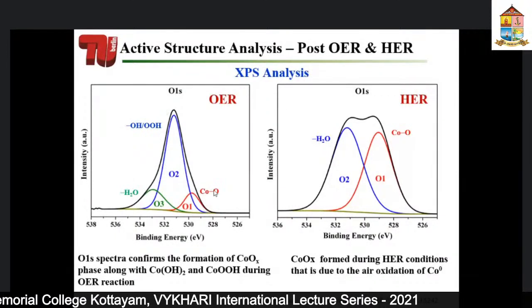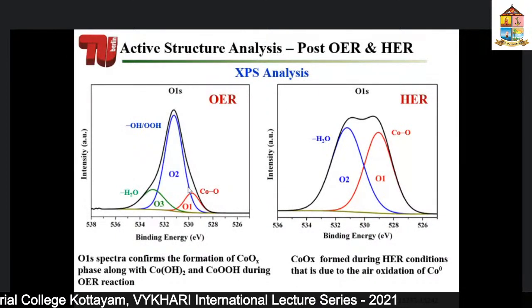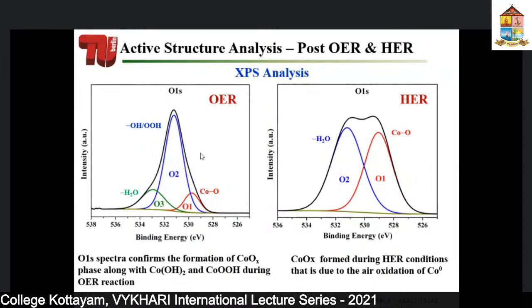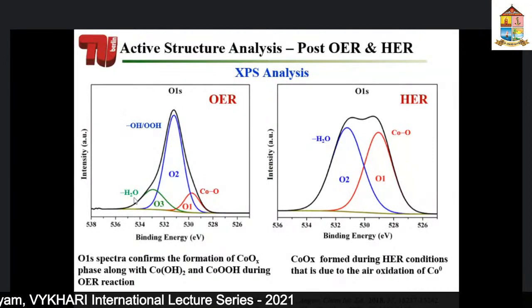You can also look into the oxygen spectra. This tells you what kind of bonding situation you have with oxygen, which is cobalt oxide bonding, some kind of oxo hydroxide here, and also some adsorbed water, which I think formed in the case of both OER, or oxygen evolution, and even hydrogen evolution.